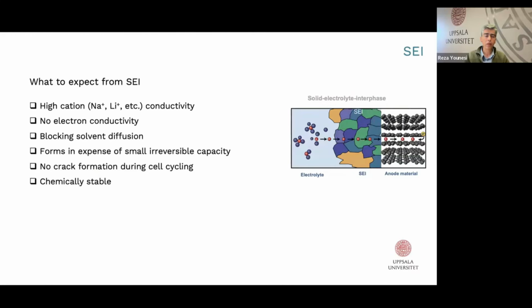As I mentioned, there are a number of points that we expect from SEI in batteries. We expect ion diffusion, no electron conductivity. It should block any solvent diffusion, and ideally it should form with very little irreversible reaction, very little irreversible decomposition of electrolyte, so the first cycle is very efficient.